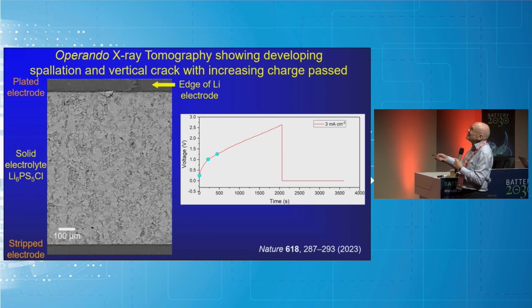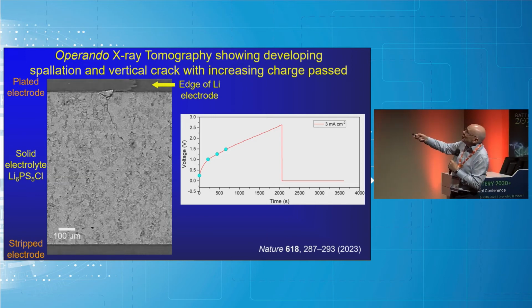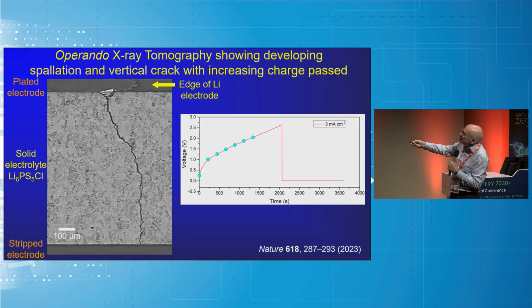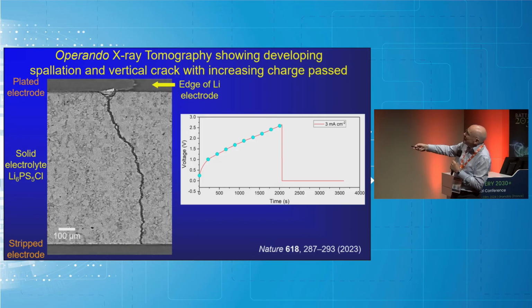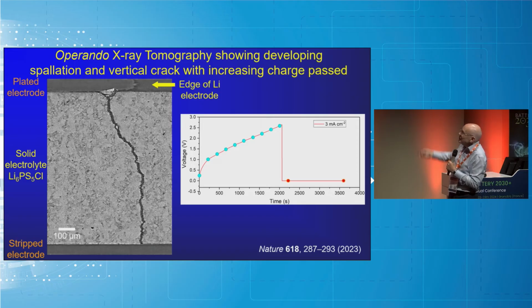So you see the dendrite. The lithium dendrites nucleate in pores, subsurface pores. They cause this effect called spalling. There you see we're already now at the other electrode, no short circuit. Crack here, only now does the lithium hit this electrode and you get a short circuit.